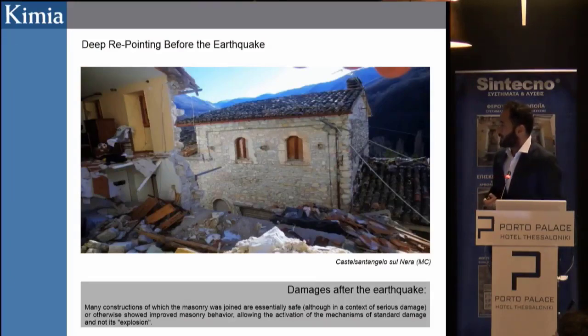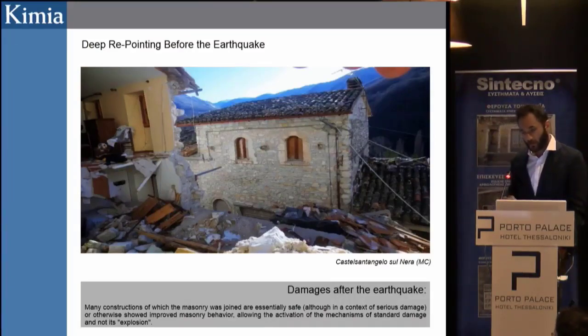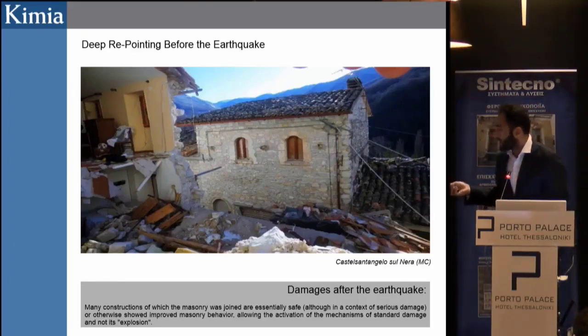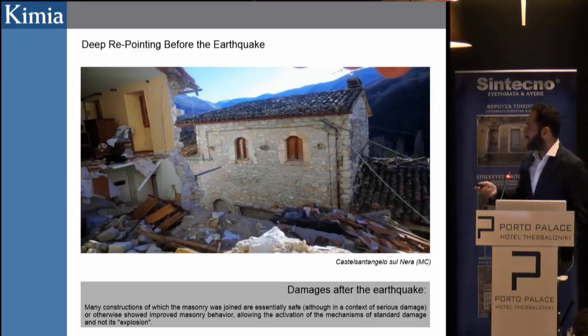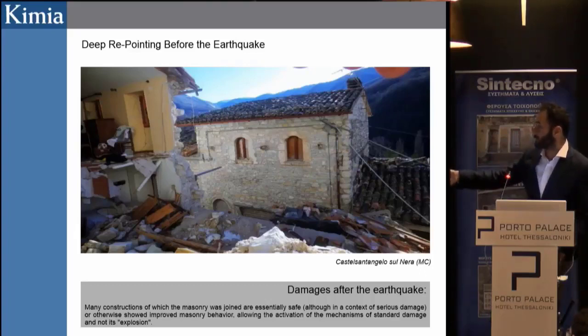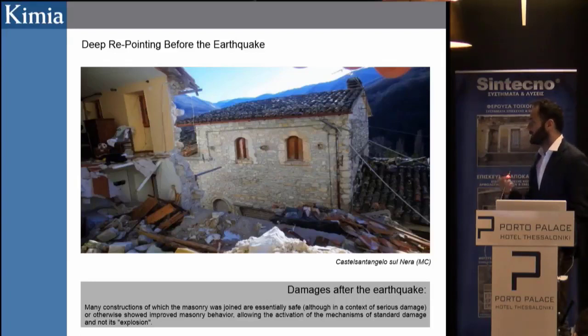One intervention which proved to be very effective in increasing the overall behavior of masonry is repointing. You see a couple of buildings. One has been very well repointed after the 1997 earthquake, and the other one has not been repointed. It's seen that a good repointing is an effective way to at least make it so that the masonry won't explode, but will activate the typical mechanisms of collapse, standard damage mechanisms, and not the explosion.